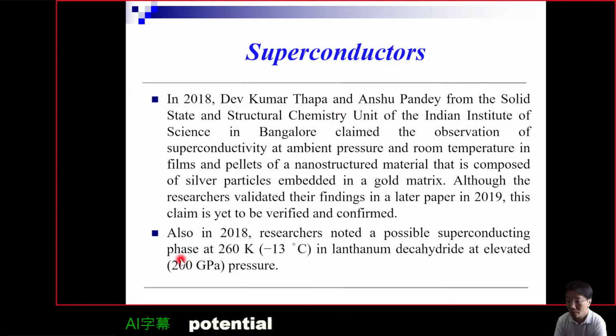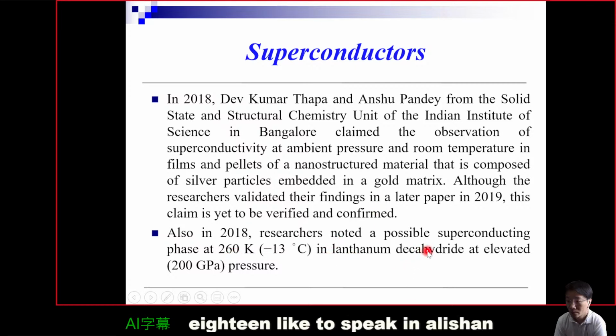And also in 2018, researchers noted a possible superconducting phase at 260 K in lanthanum decahydride at elevated pressure, which is really high, 200 gigapascal.